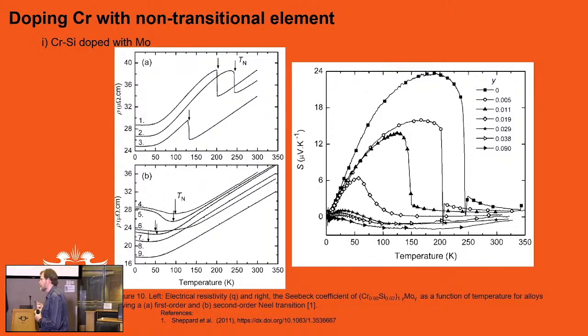And there's 2 transition points in this particular sample, particularly if we start tracking what TN is doing as a function of composition. On the right here, remember this is resistivity, so it's a current applied. You measure a voltage and it's in a particular geometry that's important that we do this. On the right here is the Seebeck coefficient. It is thermal. So what you have is a sample, you apply a small heat, and now the electrons carry the heat through the material. And you don't have this electric current that's doing the work. And again, what you see is the sharp response effectively here, almost first order in the transitions. And then becoming again smooth and quite difficult to actually track at the bottom here. The Seebeck voltages are quite small voltages that we actually measure.